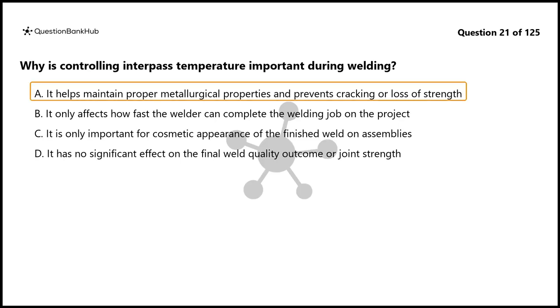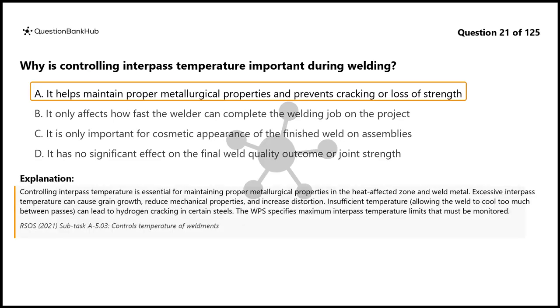The correct answer is A. It helps maintain proper metallurgical properties and prevents cracking or loss of strength. Controlling interpass temperature is essential for maintaining proper metallurgical properties in the heat-affected zone and weld metal. Excessive interpass temperature can cause grain growth, reduce mechanical properties, and increase distortion. Insufficient temperature, allowing the weld to cool too much between passes, can lead to hydrogen cracking in certain steels. The welding procedure specification specifies maximum interpass temperature limits that must be monitored.